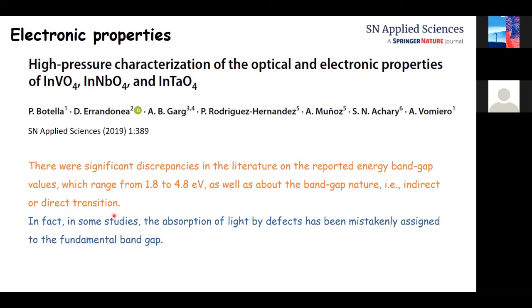So we have proved that the band gap is in the high range of values, not 4.8, but a little bit below it. And indeed, I will show that the energy assigned to the band gap in the past is not the band gap, but is absorption of light related with defects present in the sample.